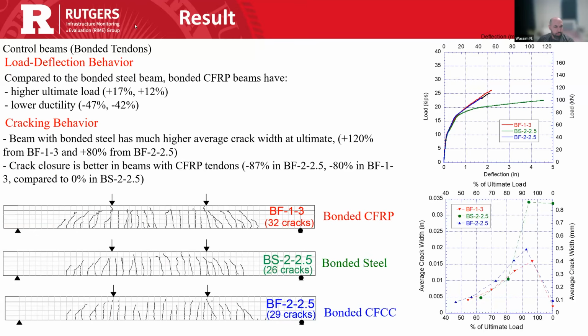Okay, so this is a summary of the main difference between beams pre-stressed with CFRP and beams pre-stressed with steel. Basically, CFRP has a higher ultimate tensile stress, but it fails at a much lower strain, which is 1.7%, compared to 5% for steel. And that results in a difference in the ductility of the beam. Although beams pre-stressed with CFRP tendons reach higher ultimate loads, they fail at lower deflections, almost half the deflection of that of a beam pre-stressed with steel.